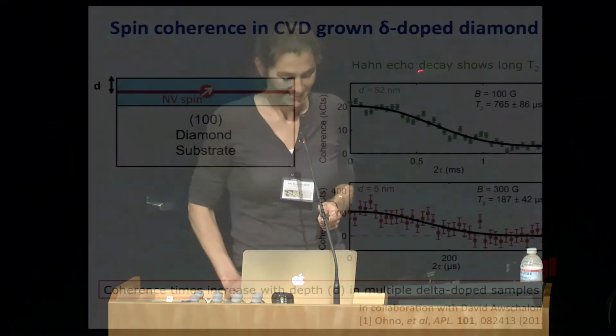To that note, I should mention, taking a step back, that when I talked about the NMR detection of oil on the surface, if we remove the oil, we still see a small signal. It's weaker, but we think it could be a nanometer-thin film of water on the surface. So the sensitivity of the NV is almost a double-edged sword. We're sensing everything, even what we don't want to be sensing.